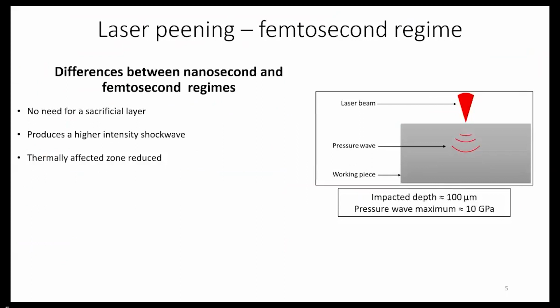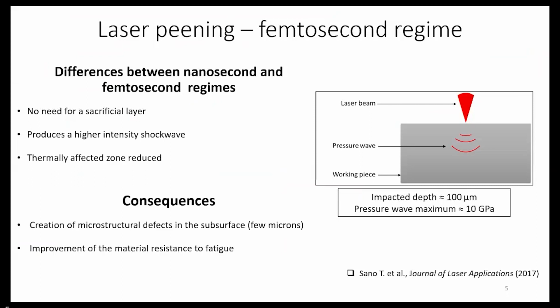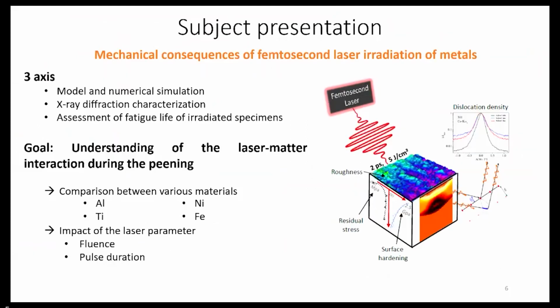So the difference, as I said, is that there's no need for a sacrificial layer, and it also produces a much higher intensity shock wave, up to dozens of GPa, and the impacted depth is smaller, around 100 microns or less, depending on the material, as we'll see. One advantage also is that the thermally affected zone is smaller than in the nanosecond regime, so it damages the surface less. The consequences are the creation of microstructural defects, especially dislocations, and the improvement of the fatigue resistance of the material.